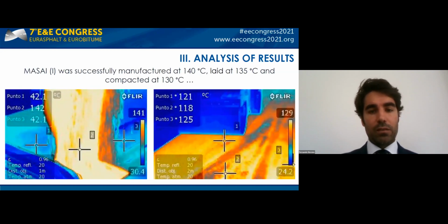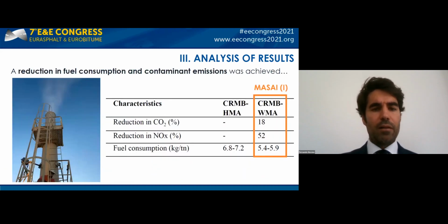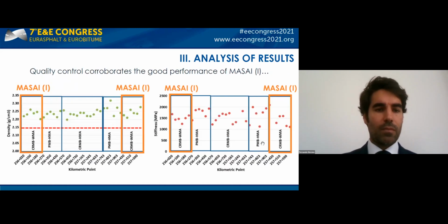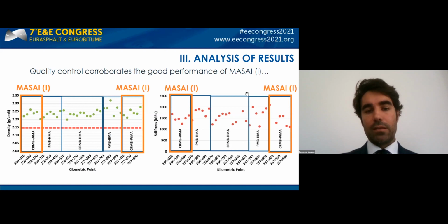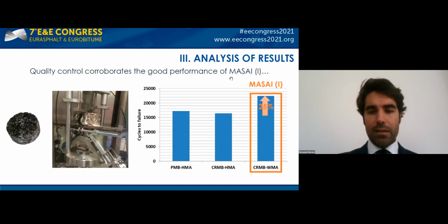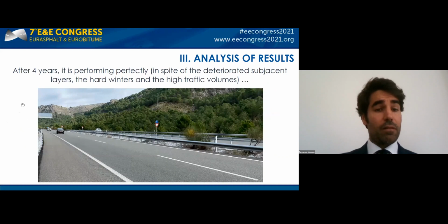The MASAI grade 1 tested was successfully manufactured at 140 degrees, laid at 135, and compacted at 130 degrees. A reduction of around 20% in fuel consumption was observed, and the contaminant emissions were also reduced, in values that range from 20% to 50%. The quality control corroborates the good performance of the MASAI, especially in terms of long-term performance under the fatigue cracking test. After 4 years, it is performing perfectly in spite of the deteriorated subjacent layer, the hard winter, and the high traffic volume that it must withstand.